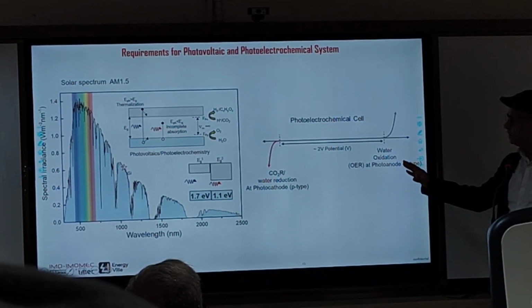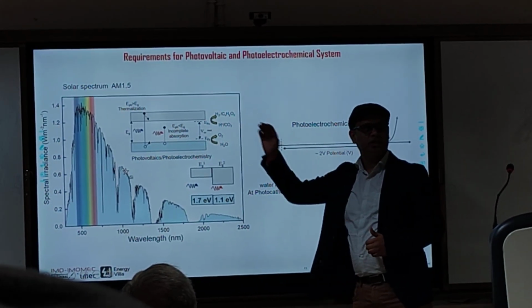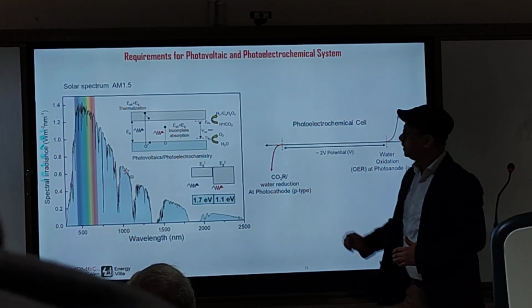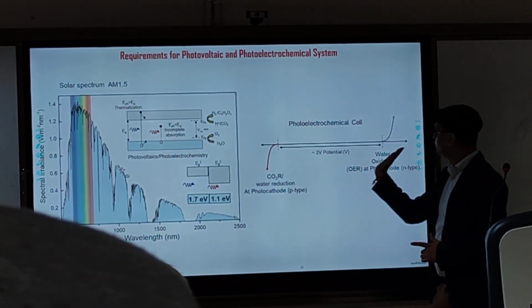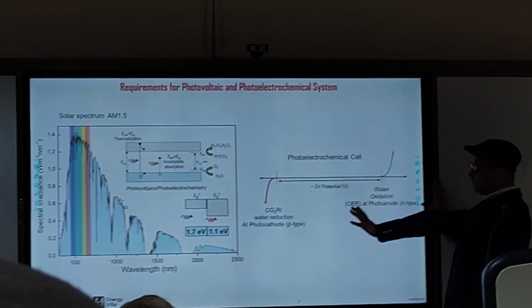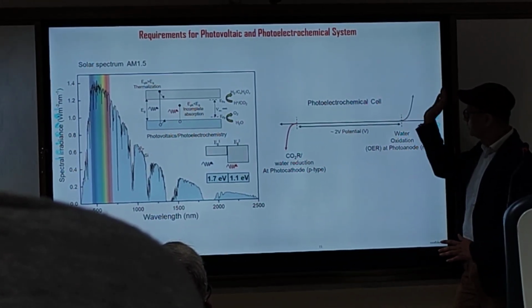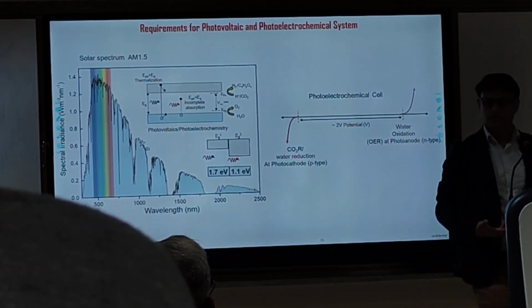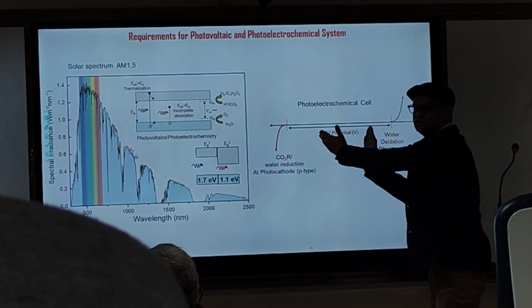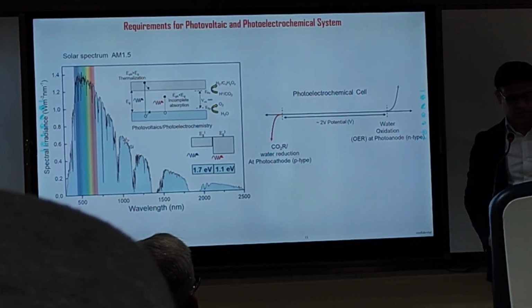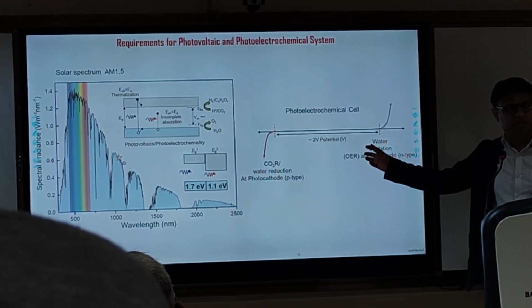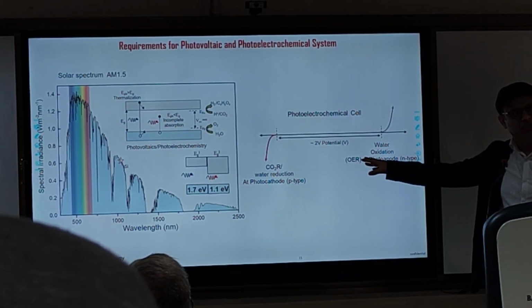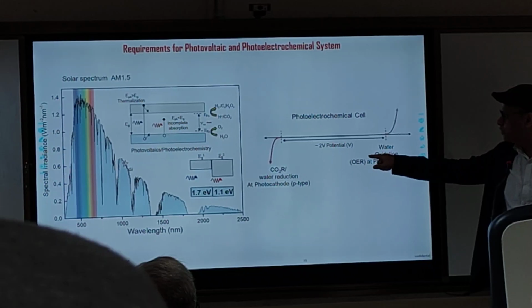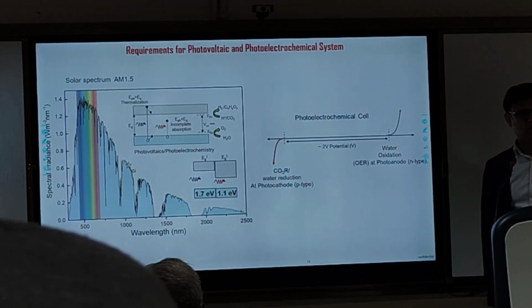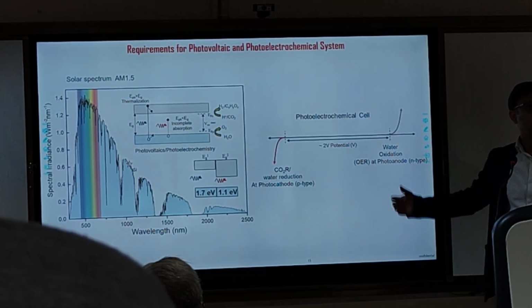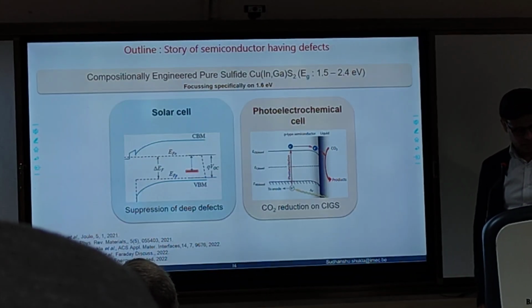How to read that? Typically, if a reduction reaction is happening, you get a negative current. Combine it with the oxidation, this part, you get the positive current, which is anodic current. Typically, when you go into the literature, you will find these curves. How fast they go determines how good your device is, and how little voltage you need to do this reaction is also important. You don't need very high energy, but some things you cannot reduce because of the thermodynamics. So 2 volts is the typical energy you need to split the water molecule or CO2 reduction combined with water oxidation. Okay, same device concept. It's just the way you use your electrons defines your final result.